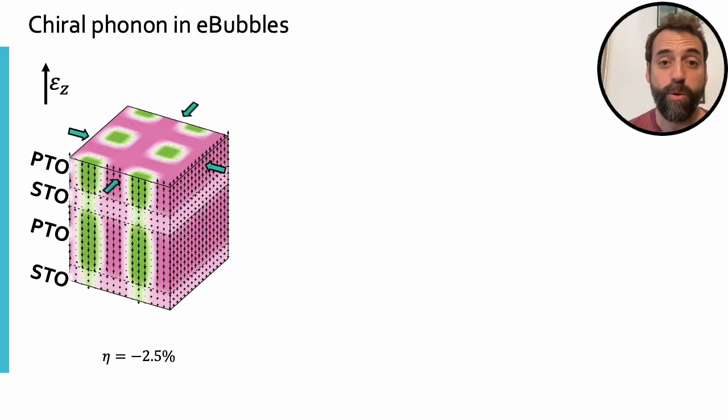Now, in bubble domains, we know that we can play with epitaxial strain to favor or disfavor the appearance of a Bloch dipole around the domain wall of the bubble. In this way, we can go to a compressive epitaxial regime where the ground state corresponds to a bubble domain with no dipole decorating the wall.